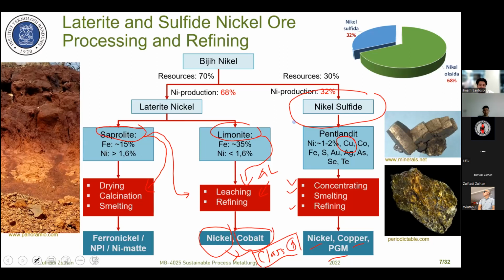And via pyrometallurgy, we use drying to remove surface water, moisture, whose content is roughly 30 to 40%. And then we charge the dry ore into the rotary kiln for calcination, to calcine the nickel ore to remove the crystal water. And then we also add reductant in this rotary kiln to reduce some amount of nickel oxide and also iron oxide. And then we smelt all the calcine from the rotary kiln in the electric furnace.